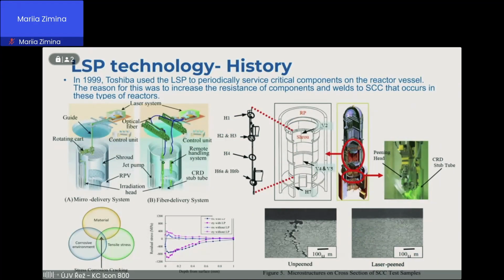The second important application, an industrial application, was in 1999 in Japan, when Toshiba used LSP to periodically service critical components on the reactor vessel. The reason for this was to increase the resistance of components and welds to stress corrosion cracking that occurs in these types of reactor. This method improves resistance to stress corrosion cracking in critical areas, like welded joints, H1 and H2 and so on,